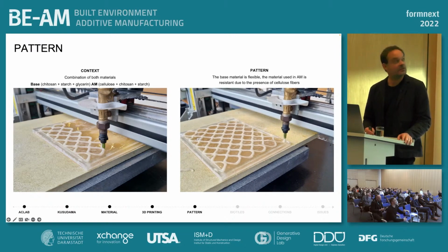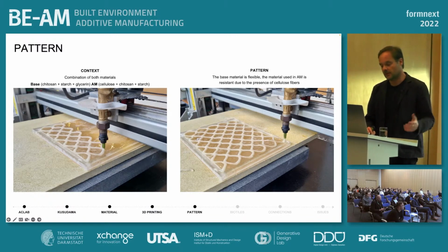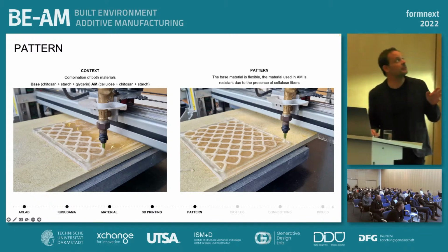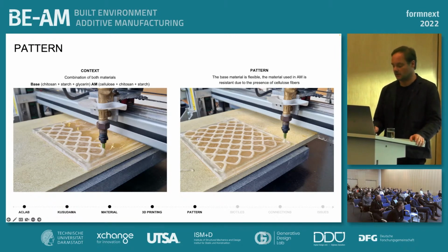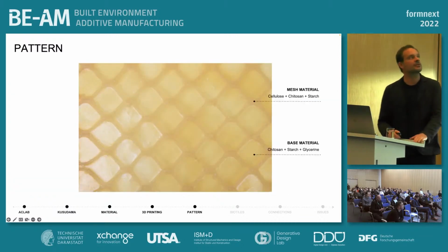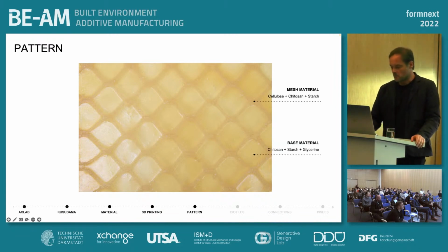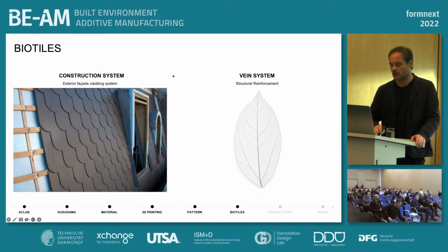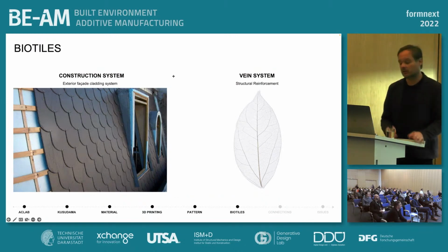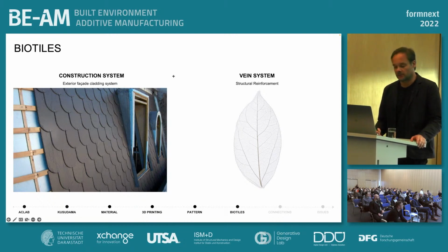The one was being used as the base for 3D printing the grid. The base is a liquid material, doesn't have any cellulose, while the grid had a certain amount of cellulose in order to provide more resistance to the composition of the material. This is just an image of one of the first specimens and tests combining these two. We see that both materials fuse slightly after drying, creating this bioplastic membrane.